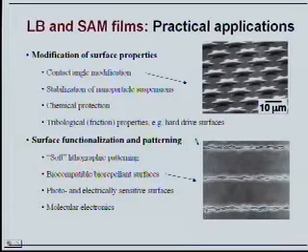So the best technology for hard drives these days is actually assembling a self-assembled monolayer of fluorinated surfactant on the surface of the hard drive. So the head actually rides on a lubricant layer. It doesn't touch it, but even if it touches, there is a lubricant layer which is only a few nanometers thick on the surface of the hard drive. So that's one of the good applications of self-assembled monolayers these days.